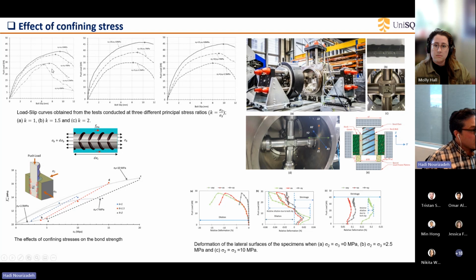So in this figure, you can see a hydrostatic condition where we have identical sigma 2 and sigma 3 from 2.5 to 10 MPa. In this one, we have a principal stress ratio equal to 1.5, and in this one, the principal stress ratio is 2. By conducting different tests, we realized that when the confining stress is set to sigma 2 equals 20 MPa and sigma 3 equals 10 MPa, we have the maximum bearing capacity, which is about 45 MPa, around 100% more than when we don't have any confining stress.